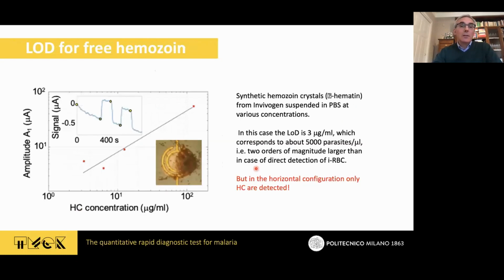That's good news. Now, the other story is, can we also measure free hemozoin? Yes, we can do that. And the beauty of the story is that in this case, also the horizontal configuration works. So that in the horizontal configuration, we are only sensitive to hemozoin. Now we try with a similar calibration curve, but in this case, the limit of detection in terms of parasites per microliter is 5,000. It's much higher than in the case of the detection in infected red blood cells. And the reason is very simple. We are really efficient in capturing hemozoin, but they are extremely small, which means the volumetric fraction will be small, the signal is small. At a given moment, you will encounter the limit of detection, which is due to the noise of your system.